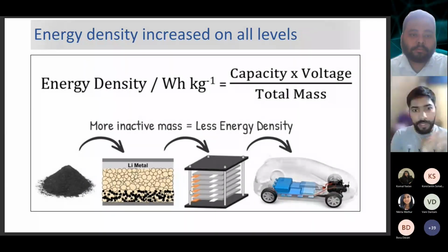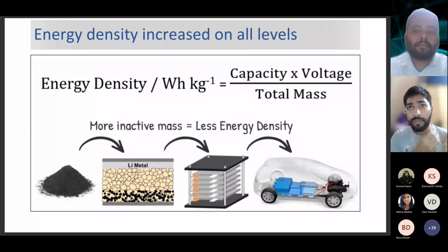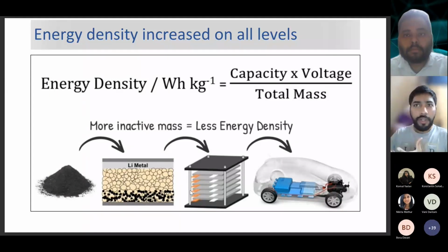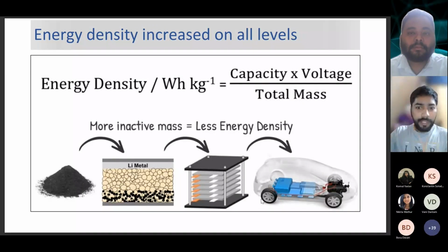So coming back to the energy density part, we are able to have more energy density on the cell because now we have the possibility of using a high energy dense lithium metal. When we say that solid state batteries are more energy dense, it's just that here we have the possibility of using lithium metal. That's it. The electrolyte or the technology itself is not improving the energy density directly. It's basically the solid state electrolyte allowing us to use a high energy dense anode, which in turn increases the energy density of the cells. But this stacks up, because now we have the energy density gain on the cell level and then on the module level and on the pack level.